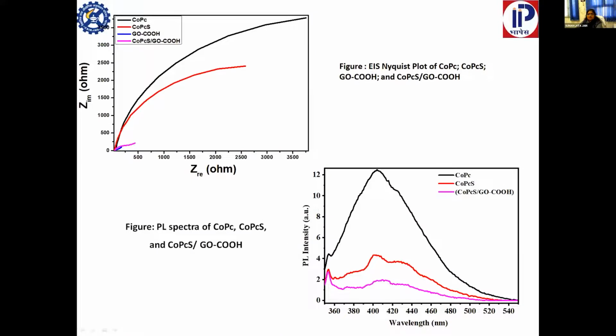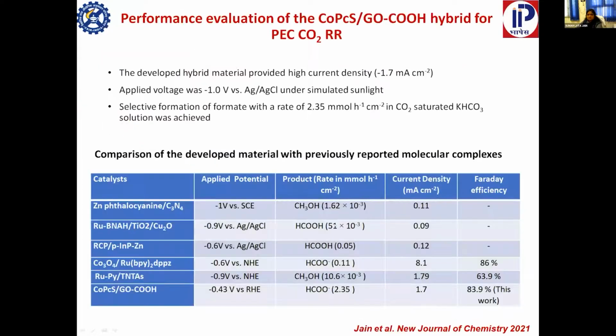Similarly, if we look at the impedance spectroscopy, this lower arc is showing the inhibited or minimum recombination of the electron hole pair and the availability of the charge carriers for the reduction reactions. Similarly, if we look at the PL, the hybrid system is showing the minimum recombination of the electron hole pairs, meaning the electrons and holes are available for the desired reactions. So if we look at the performance of this material